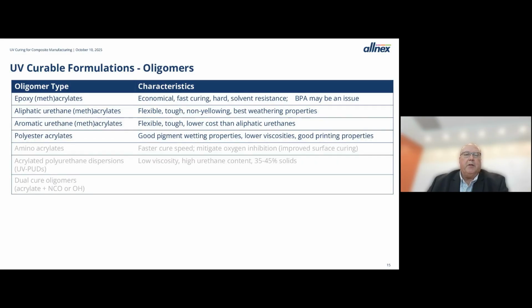There's a lot of different oligomer types, but in general, we tend to stick to epoxy methacrylates or epoxy acrylates and urethanes, and sometimes polyester acrylates as well. Epoxy methacrylates are basically equivalent to vinyl esters without the styrene, so it's the same general structure. But these are economical. They're fast curing. They're a good base for a lot of different polymer matrices. The urethanes are tougher materials, can be very good for exterior applications, and the polyesters are in general there to act as a co-resin. They can help with pigment or filler wetting properties, blend in to get lower viscosities, that sort of thing.